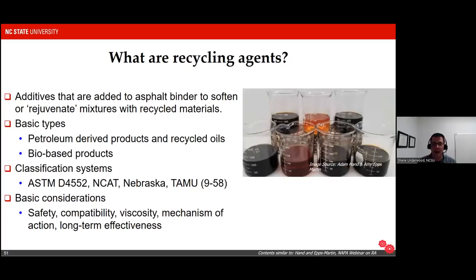Now, dosage-wise, it very much depends on the specific recycling agent, on the target of the rejuvenation, and on the RAP stockpiles you have. So if you want a rule of thumb, a good rule of thumb is somewhere between, I would say, 1% and 5% recycling agent dosage, based on the studies we've been involved in. There are probably cases that are below that limit and some that are above that limit.